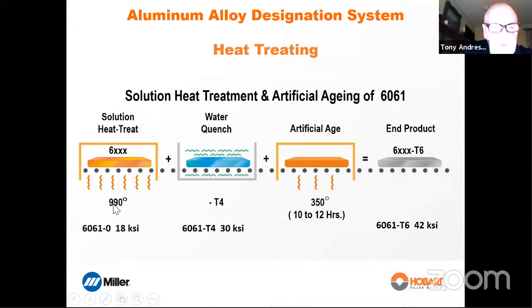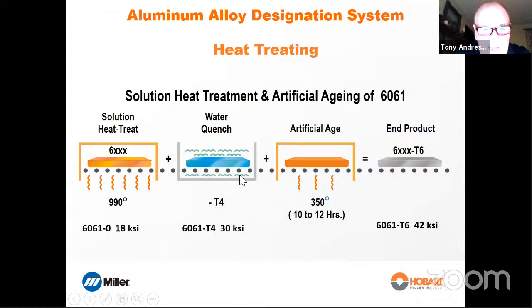If we take that material and we heat it up to 990 degrees and then quench it in water, we change its temper from O to T4. The T4 temper is solution heat treated only. And we increase the strength by doing that from 18 KSI to 30 KSI. So we've heated the material to 990, quenched it in water, and increased the strength substantially.